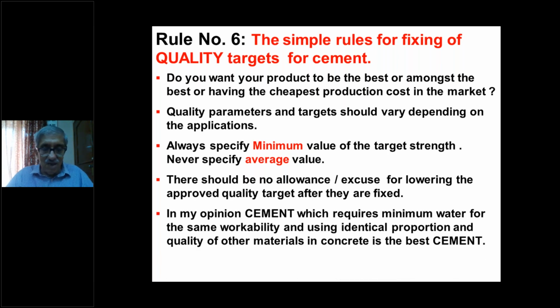In my opinion, cement which requires minimum water for the same workability, using identical proportion and quality of materials in concrete, is the best cement. So it is very, very important that cement, and when I say cement I mean even the consistency which we measure in the laboratory before casting the cubes, should have the same consistency and identical proportions.